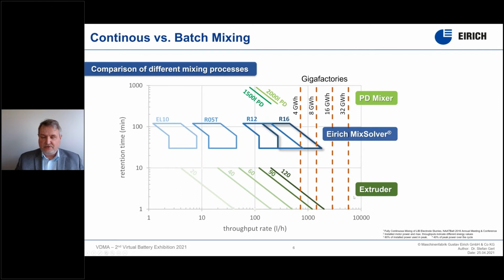On the other hand, we have the continuous extrusion systems with different screw diameters, which is also running in the range of retention time of roughly 1 to 10 minutes, in the factor of 10. And both systems have the problem that if you increase the retention time, you decrease the capacity. And this is not so different with an extruder. So you are not independent in retention time and throughput rate. So this changes your product if you want to go for a higher capacity or for lower capacity.